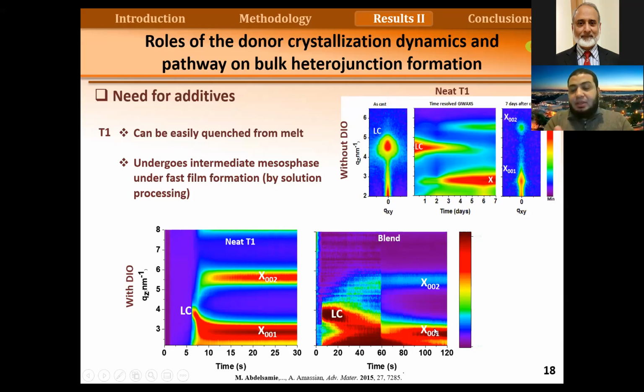And we try to link this also with crystallization from melt. We have found that if we melt this material and cool it very fast, we can also quench it into a liquid crystalline phase. So this material has a problem in the self-assembly. When it tries to self-assemble, it has an intermediate metastable phase, which is weakly ordered and has low absorption and low conductivity, so it is not appropriate for the final product. But we need to use some additives to transform this unwanted phase into a wanted phase.